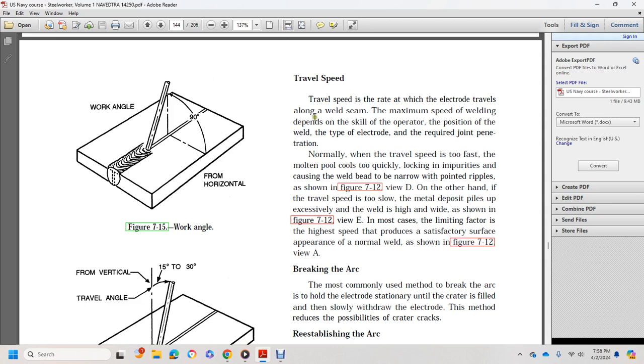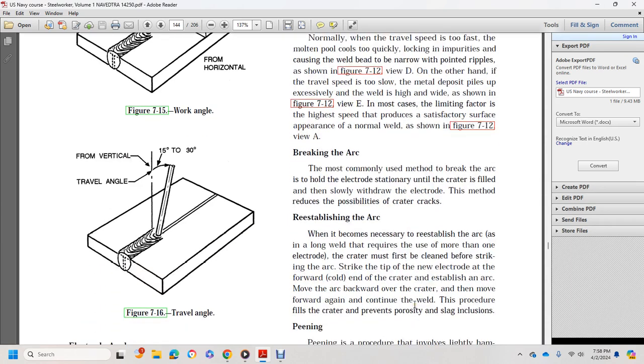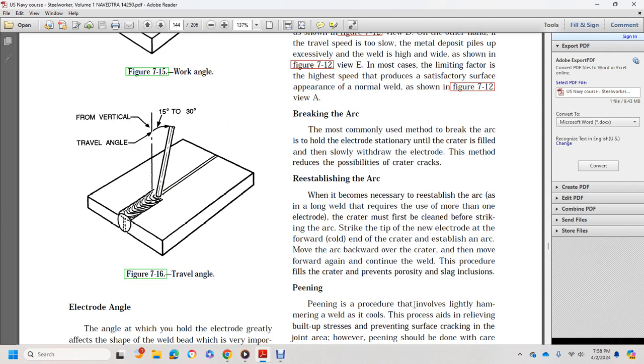Breaking the arc. The most commonly used method to break the arc is to hold the electrode stationary until the crater is filled, then slowly withdraw the electrode. This method reduces the possibility of crater cracks. Re-establishing the arc. When it becomes necessary to re-establish the arc in a long weld requiring more than one electrode, the crater must first be cleaned before striking the arc. Strike the tip of the new electrode ahead of the crater on the cool end and establish an arc. Move the arc backward over the crater and then move forward again and continue with the weld. This procedure fills the crater and prevents porosity and slag inclusion.